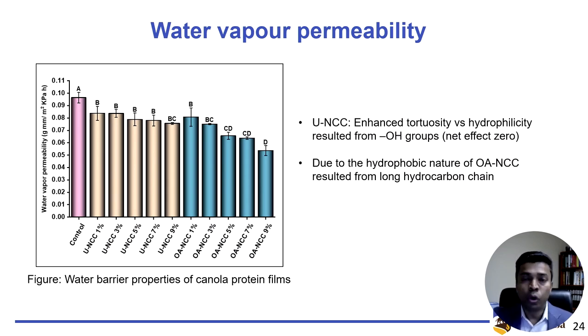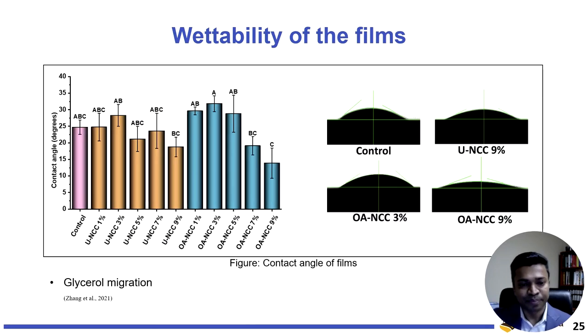Water vapor permeability is another thing that we looked at. But unlike in the previous study, we did see a unique reduction in the water vapor permeability of the oleic acid grafted nanocellulose reinforced packaging materials, which is ideal. Then we looked at the wettability. Theoretically, we should have seen a better contact angle compared to the previous study, but we did not.